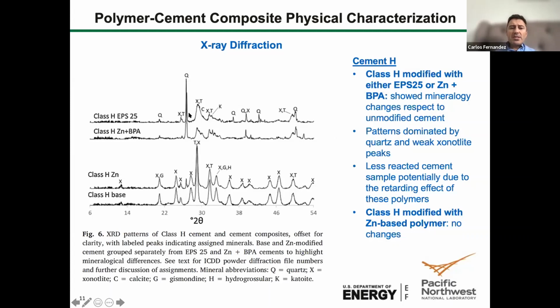But we see some changes in the diffraction pattern compared to cement H for the thermoset epoxy and for this second polymer. The reason is that they act as a retarder, as I showed you before. So after 24 hours, you still see that the material hasn't formed the final xonotlite, calcite, katoite, portlandite, and sonolite that we see for other polymers.